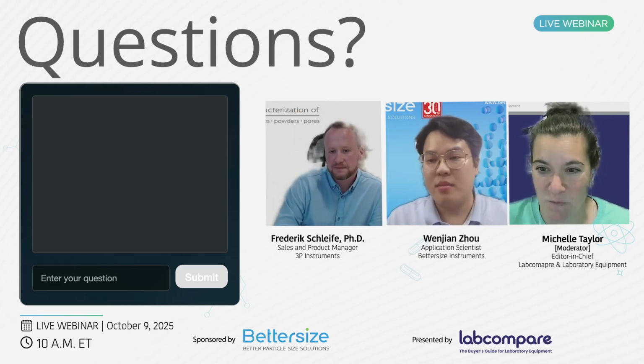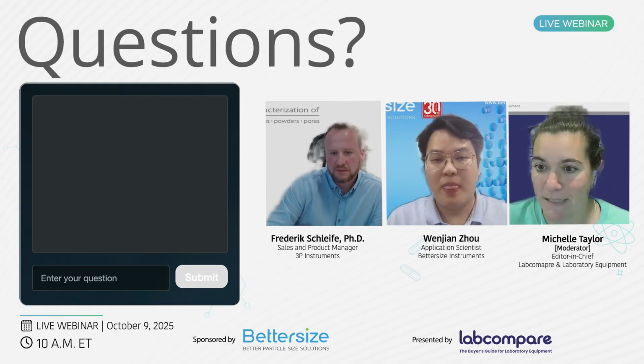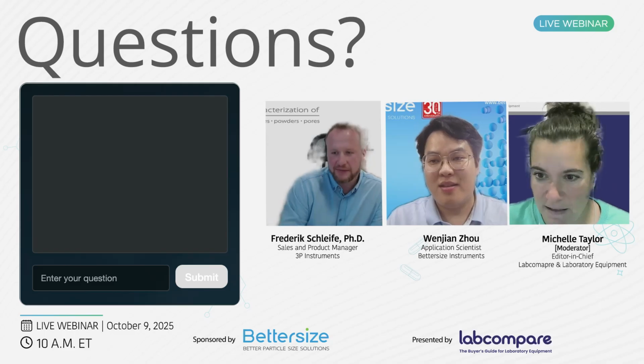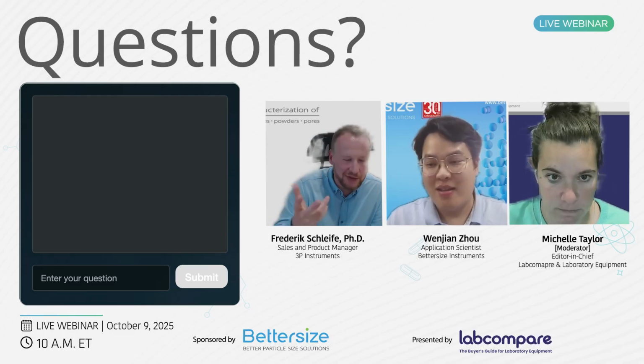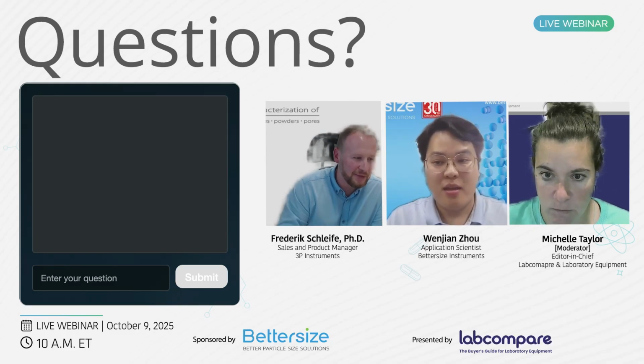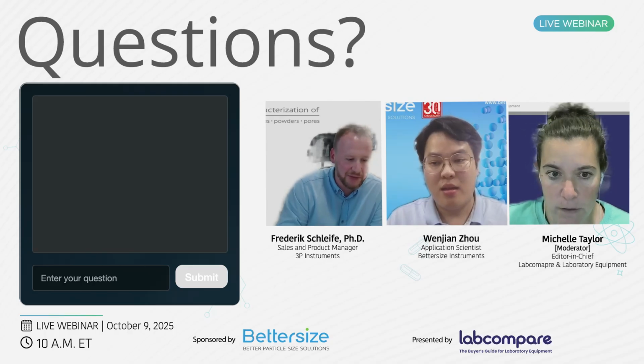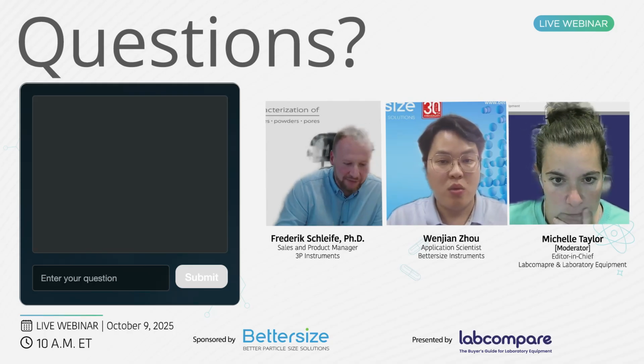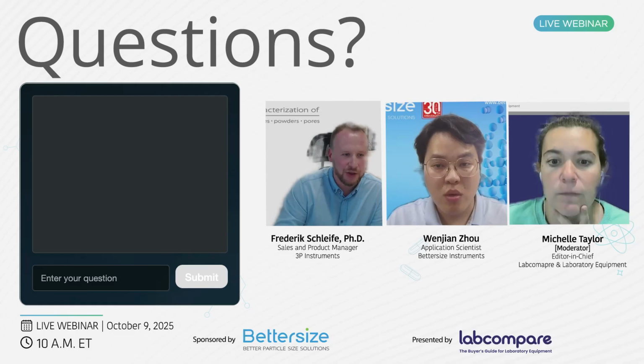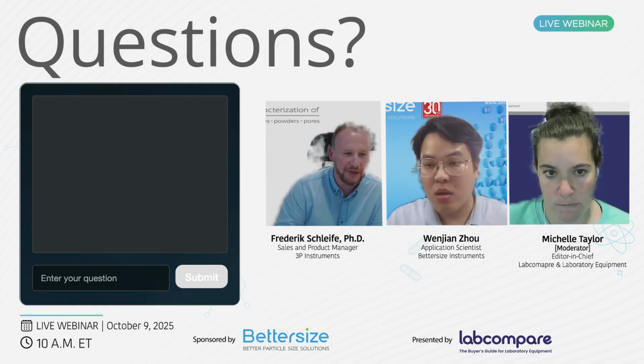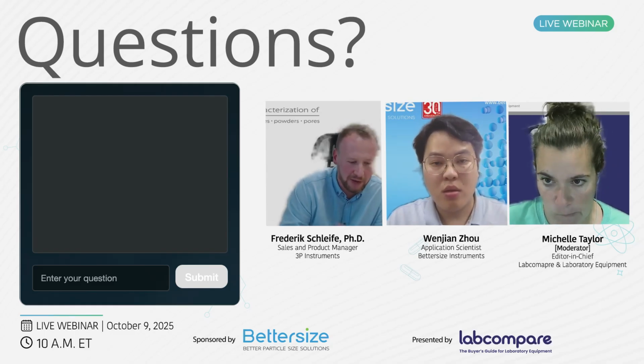Freddie, anything to add there, or self-explanatory? Yeah, no, nothing really. Of course, this is possible if it's two different materials, but you need to know that what we get with laser diffraction is a volume-based distribution. So therefore, from pure laser diffraction, you cannot directly distinguish which type of material is what. But of course, you would see that one is smaller, one is larger.